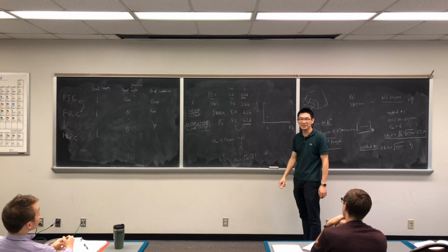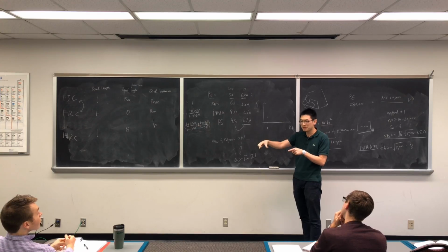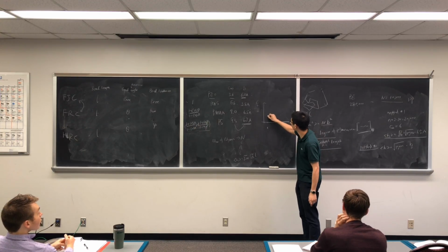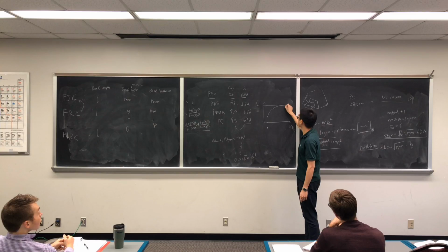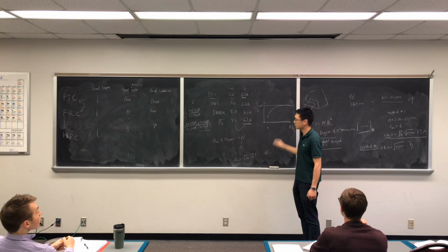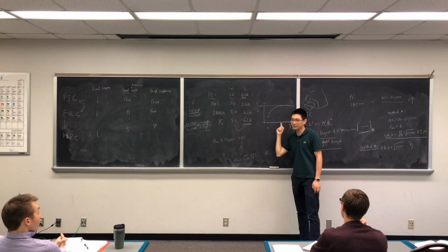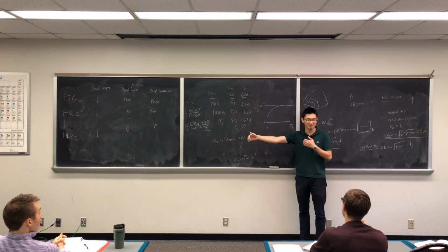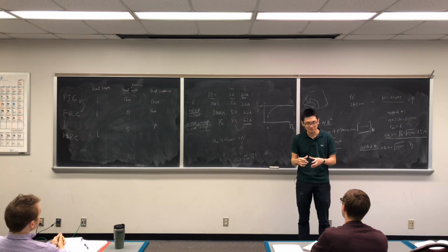So it's going to start here, and now you have 2 bonds, 3 bonds, and as it goes on, this will increase. And it will reach a value and plateau out at infinity. We call it C infinity, the characteristic ratio. As you see, this depends on how long your chain is. Otherwise, your end-to-end distance will depend on whether your degree of polymerization is a short chain or a long chain.